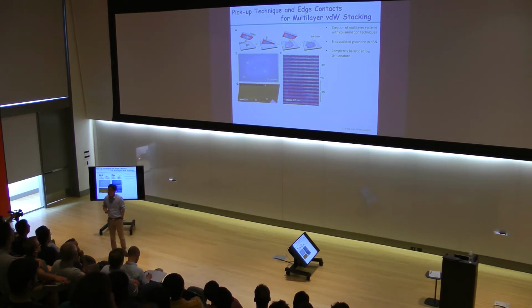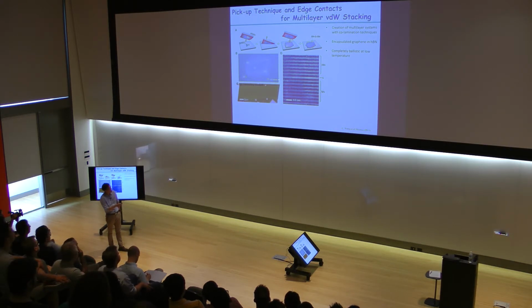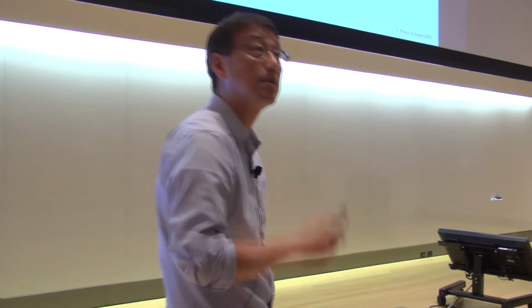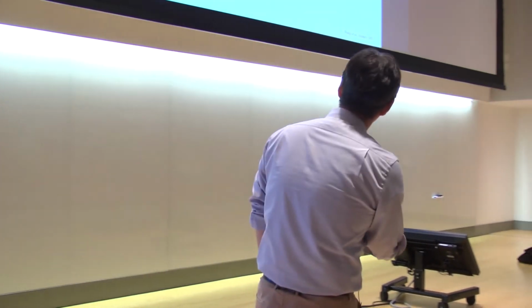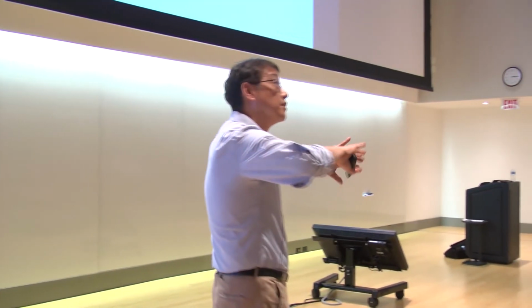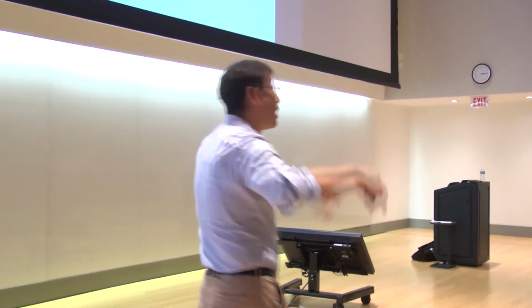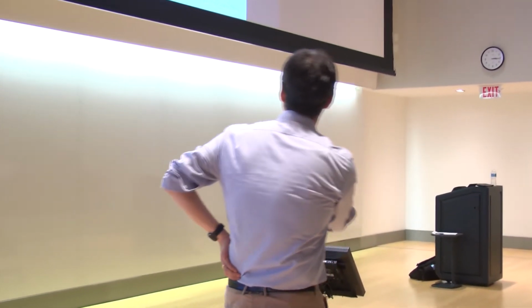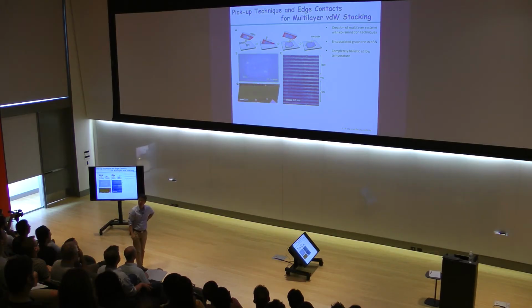But the important part is, if you just do it in a really controllable way, as you see in this cross-sectional TEM image, here is graphene encapsulated between the boron nitride. The important part is that this interface, especially this hetero interface between graphene and boron nitride, is extremely clean. There are no single atomic defects you can see in this cross-sectional TEM image. All this dirt and impurities are basically squeezed out from this van der Waals interface, such that you have atomically sharp interfaces. Not only can you get this